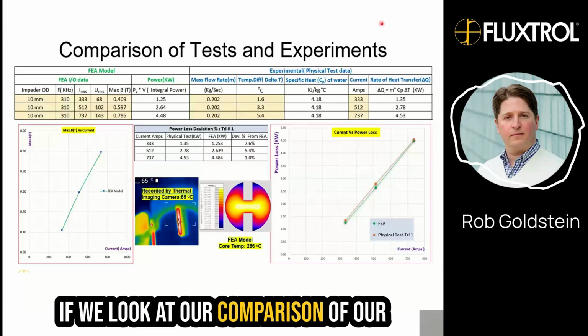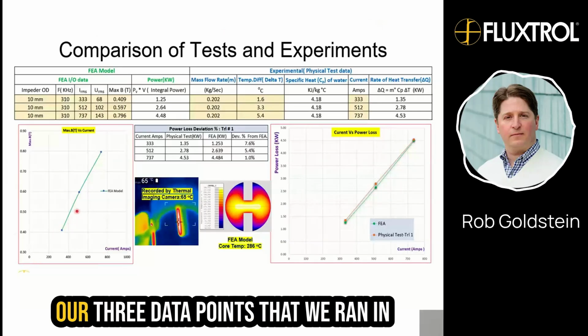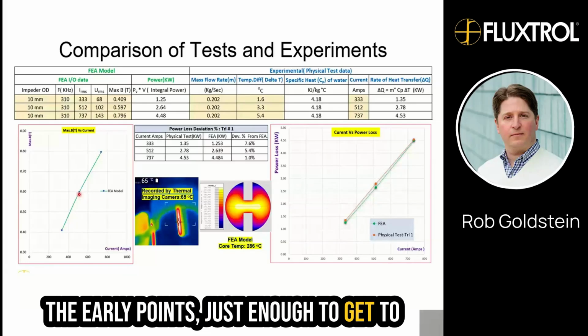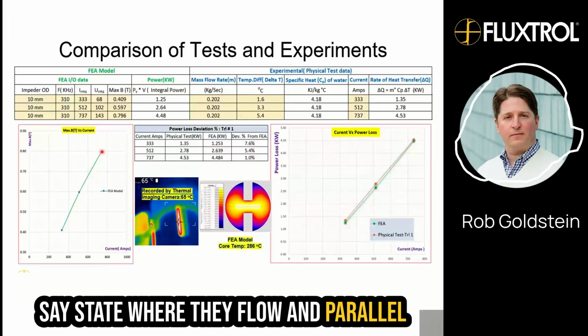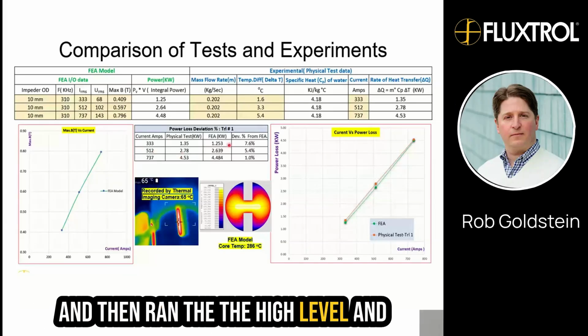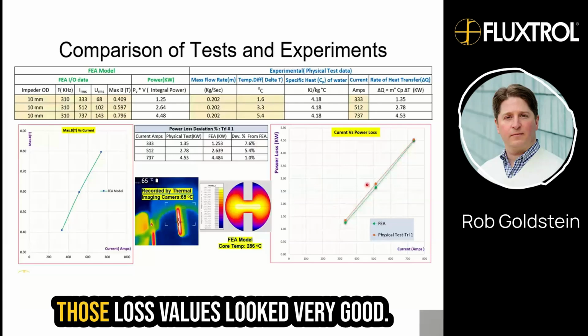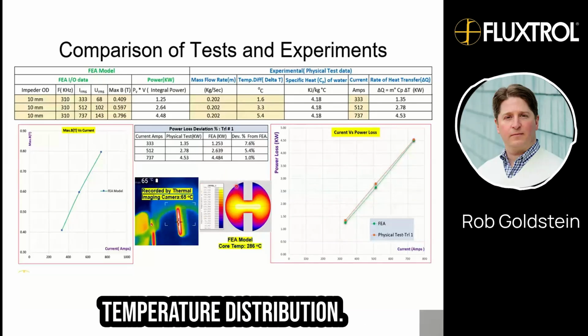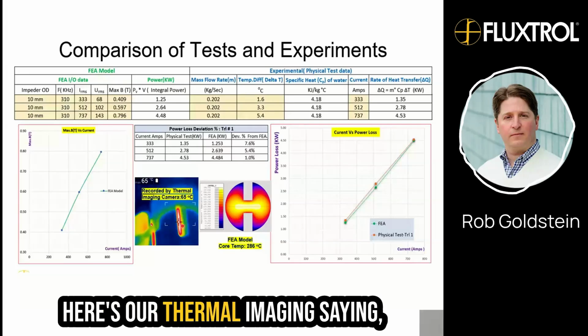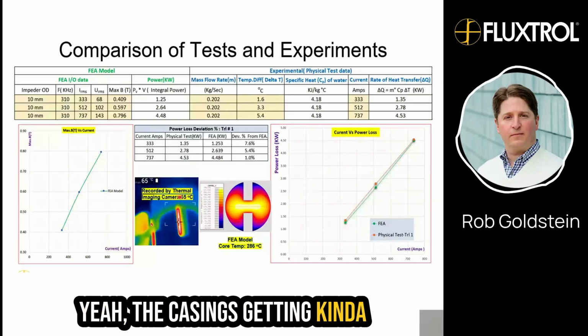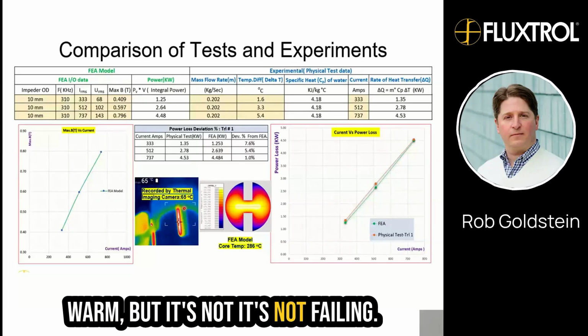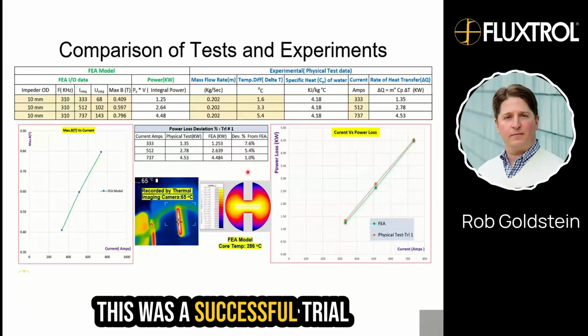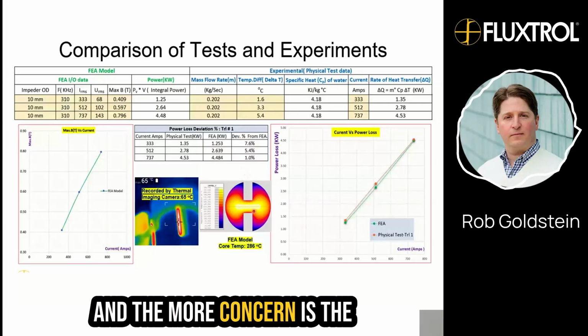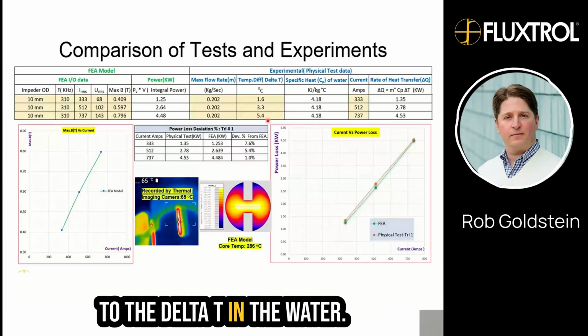If we look at our comparison of our tests and experiments here, so here's our 3 data points that we ran. In the early points, just enough to get to steady state where they're flowing parallel, and then ran the high level, and those loss values looked very good. Here's our FEA of the internal temperature distribution. Here's our thermal imaging saying, yeah, the casing's getting kind of warm, but it's not failing. This was a successful trial. And the more concern is the local temperatures as opposed to the delta T in the water in this impeder.